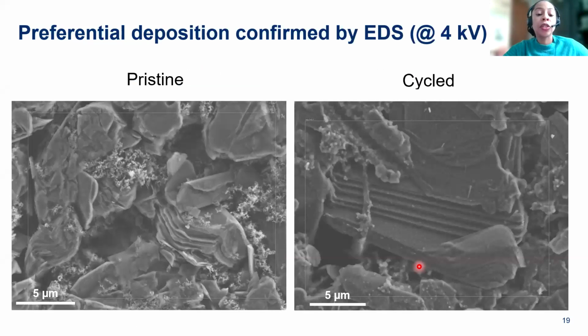And we also did some SEM and EDS at the University of Manchester. So we looked at pristine anode material, which is material that has not been exposed to any electrolyte and has not been cycled, and we see some carbon black and these nice graphite layers as well. We see the same for cycled samples, which were cycled 3 times in electrolyte. And we wanted to compare what types of signal we get when we look at pristine versus cycled.